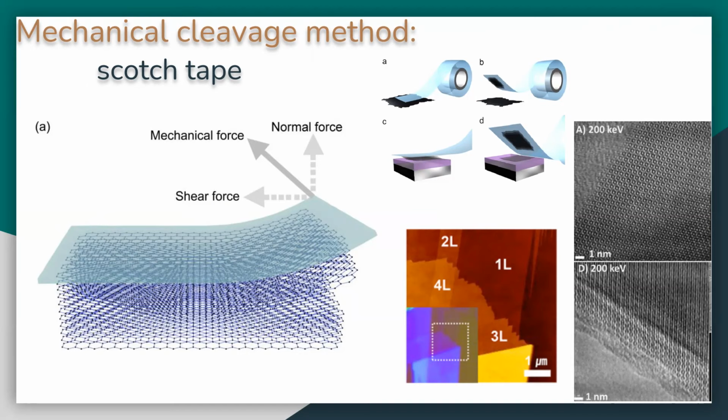The force balance near the contact point can be used to calculate the specific surface energy of the monolayer, which is a direct measurement. And from the monolayer, the radii of a forced bent sample can be established, and determination of the reversibility without fracture can be observed. And this type of behavior is good for use in flexible electronics, such as mobile phones that are subjected to extreme folding conditions.